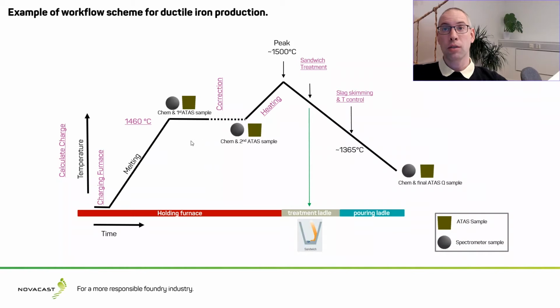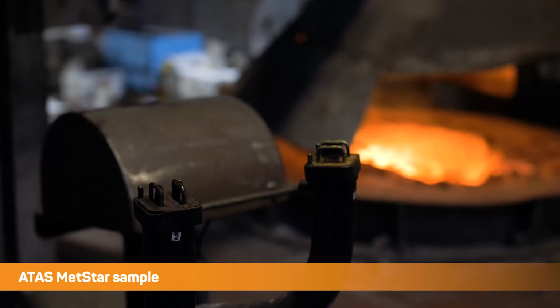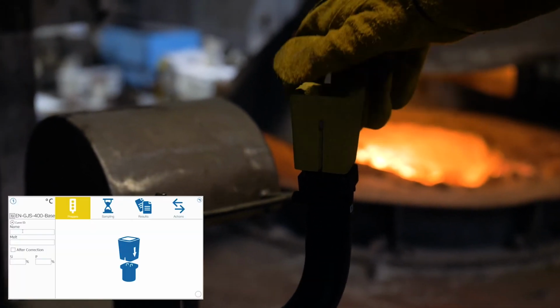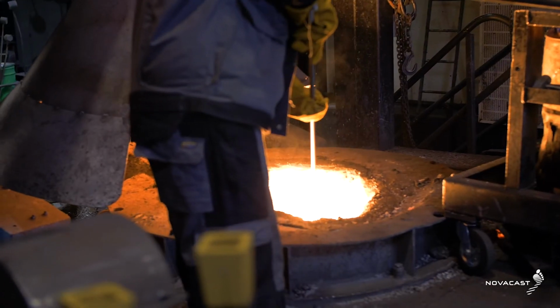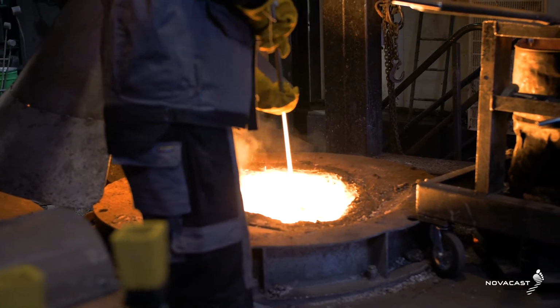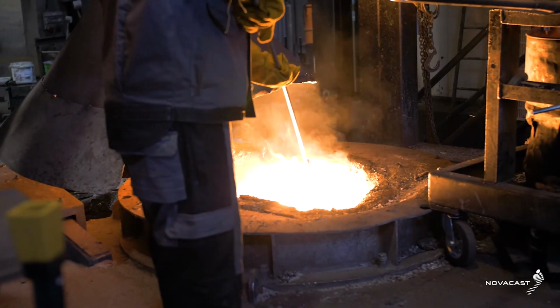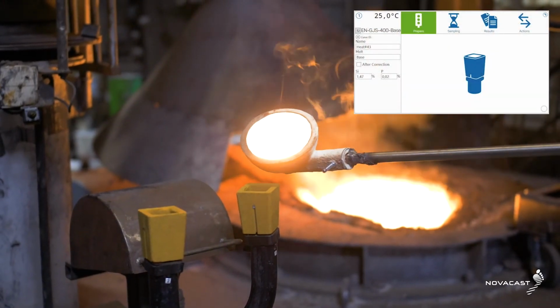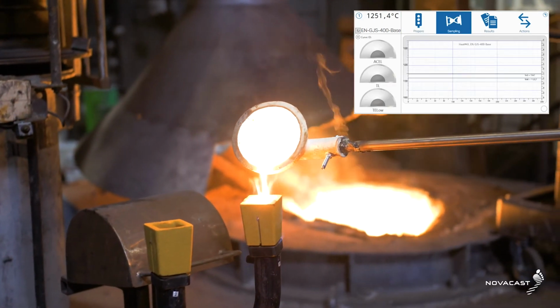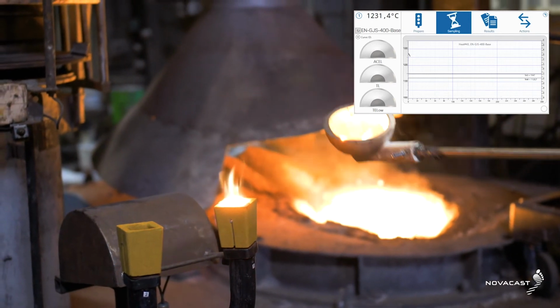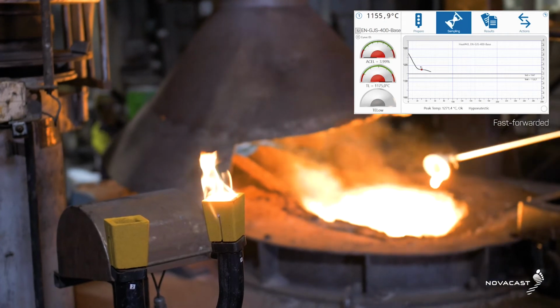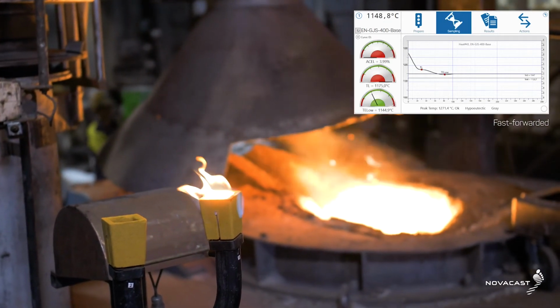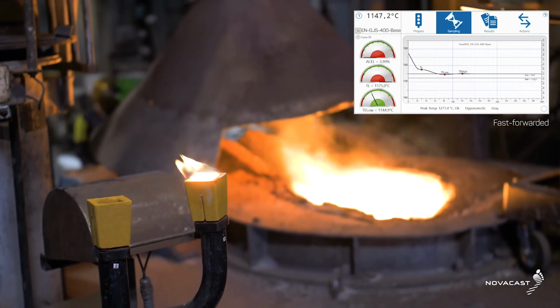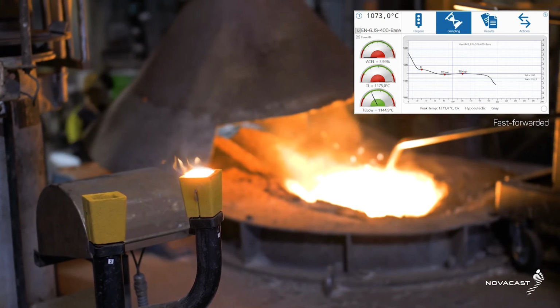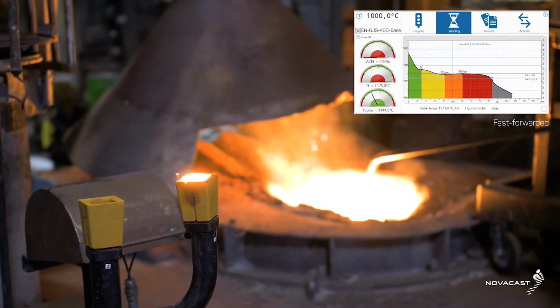Also, we have to take an ATAS sample. This is a first ATAS Master sample to control metallurgical quality. So we can see that operator has placed a plain sand cup on a measuring unit. Then he has taken a spoon, ceramic spoon preferably, flushed it 3 times, and carefully pours into the plain sand cup with one steady stream. We see ATAS Master has started to evaluate the quality, and first point, which is liquidus, it's directly connected to ACE, which is active carbon equivalent, and in this case it's out of the specification, which we actually would not like to have.